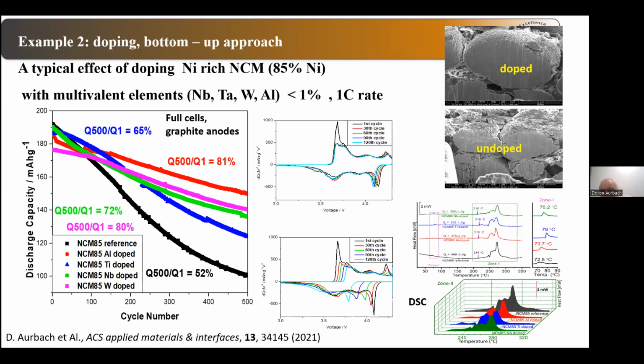But what is most important is the structural stability. What I show you here in the right corner is that we take electrodes, and by focused ion beam, we cut them in the middle. So we have cross sections of particles, and we look at the structure by scanning electron microscopy. We see that when we have doped material, after hundreds of cycles, the cross section is smooth. We retain the initial smooth and uniform morphology, while with reference materials, when we have fast capacity fading, we have a lot of cracks. We see the morphological instability. So we have a very nice correlation between the chemistry, morphological studies, and thermal studies.